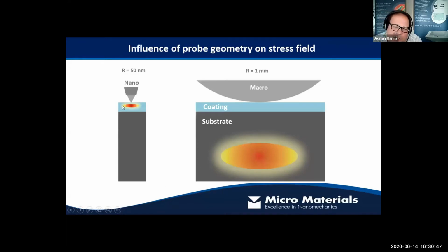probes. So in a nano impact test, we tend to use a small radius probe, and that tends to put the maximum stress point quite high up in the sample, actually inside the coating itself. And typically, very often, where a failure occurs is actually the interface between the coating and the substrate. So it's nicer if we can move this maximum stress point down a bit. So we can do that by using a bigger probe.